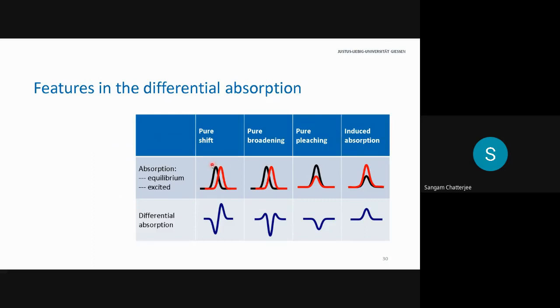Again, a cut, copy, paste error. The resonance can shift. So in differential absorption, you will see this. This resonance can broaden, which means it doesn't shift like I've shown here, but it gets broader. If it gets broader, it means the area under the curve stays the same. The maximum goes down and the full width half max increases, which actually means that you get this type of a line shape shown at the bottom.